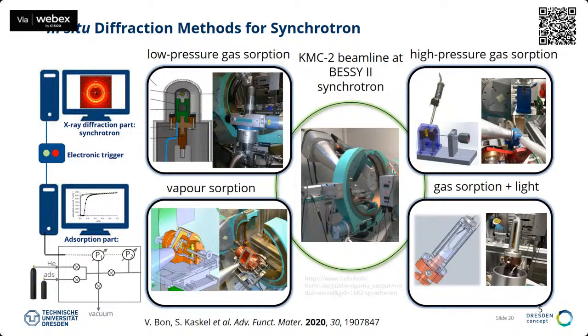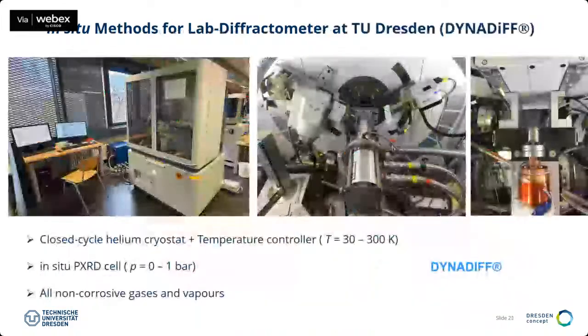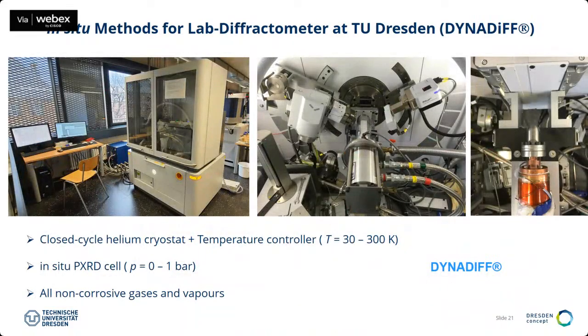Of course, traveling to a synchrotron is always quite expensive and takes time, and it's difficult to get measurement time. Therefore, we also developed this as a diffractometer in our laboratory. This is a commercial PANalytical diffractometer where we adapted our in situ methodology. Here you see the beryllium dome, which is X-ray transparent, and this can operate at very low temperature, down to 30 Kelvin, and at pressures up to 1 bar. It can be used for non-corrosive gases.